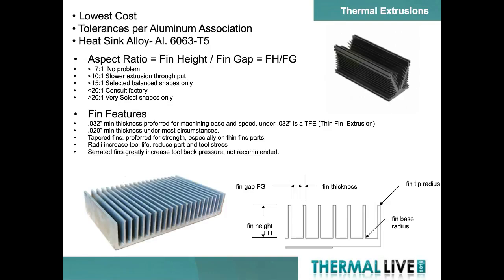As I said, most of the extrusions we use are aluminum. They are made of 6063, which is extremely easy to push and also has a very high thermal conductivity. When you look at any given shape, you want to look at what is the overall width, what is the height, and also the aspect ratio and fin thickness. The aspect ratio is defined as the fin height divided by the fin gap, and we use that as a way to determine how hard this shape is going to be to push.